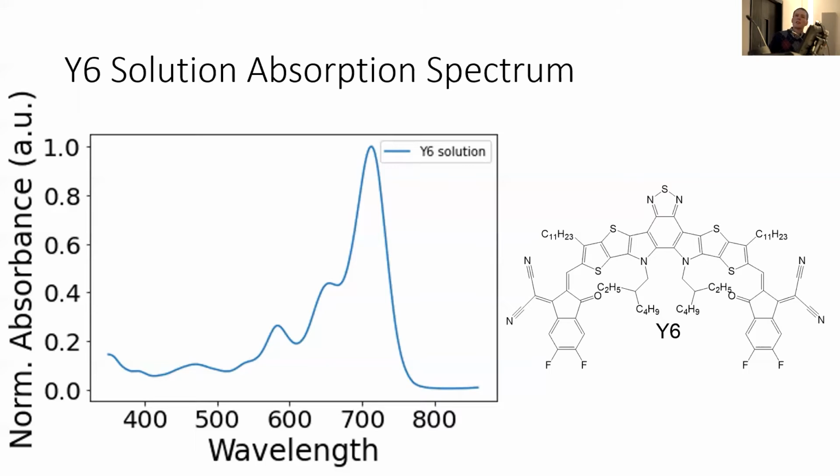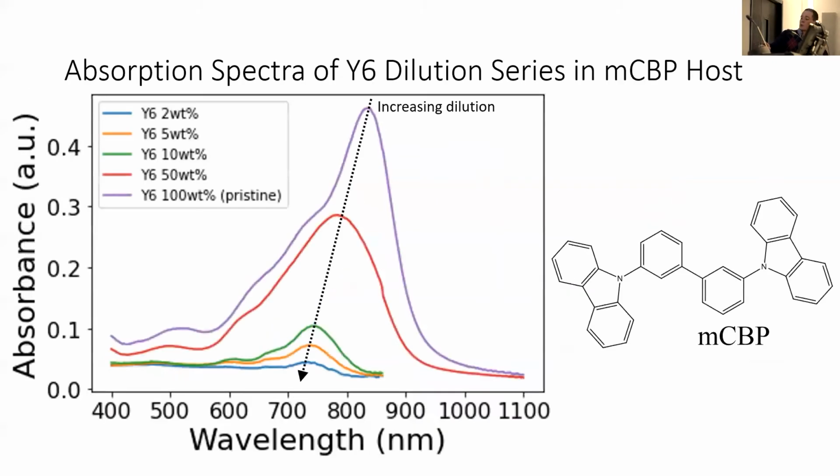First of all, you have a bit of a problem because these molecules absorb pretty much everywhere where most Raman spectrometers have lasers. Our Raman spectrometer will do 405, 532, and 785, but even at 405 you've still got a bit of absorption.